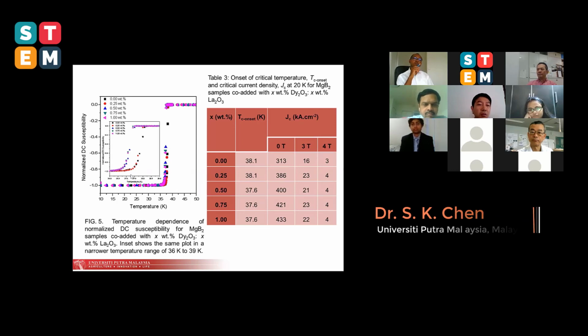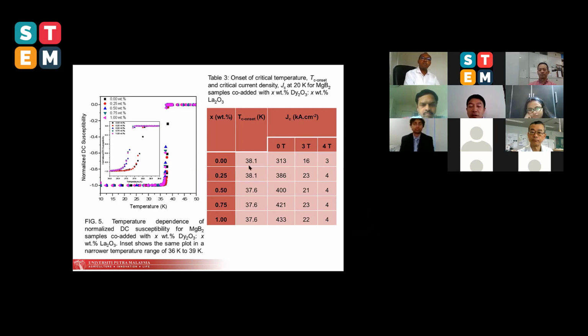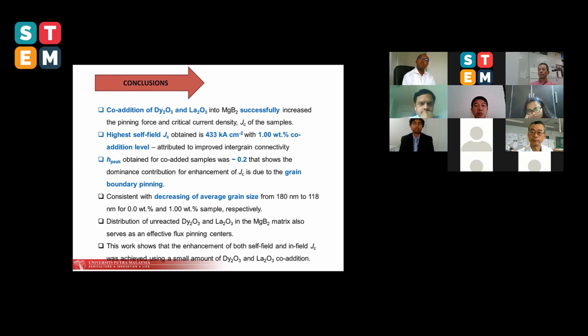Here is the Tc plot. As I mentioned just now, the Tc did not decrease much, about 0.5 Kelvin, as we expected. And the Jc at self-field as well as applied field also increased compared to the pure samples. In conclusion, we show that a very small amount of co-addition of dysprosium oxide and lanthanum oxide in MgB2 can increase the flux pinning and also the Jc of the sample. The highest self-field Jc that we obtained is about 433 kA per square centimeter, achieved in the 1 weight percent co-addition sample.